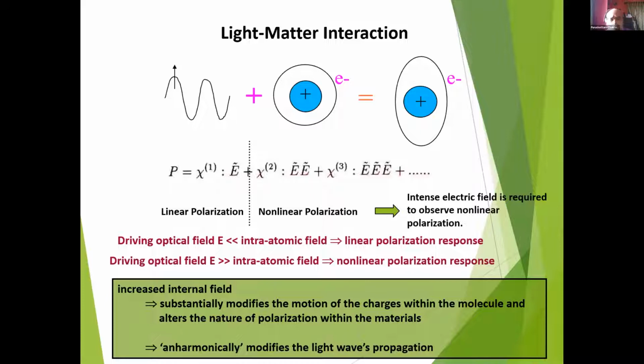Now, polarization is, of course, where the chi2 comes in for the higher optical fields, and chi3 and chi4, chi5, and so on. I will be talking basically about the chi3 part, because I'm talking about photonics, I'm talking about the glasses, I'm talking about the metal quantum dots which are embedded in the glasses. Now, when the driving optical field is much smaller compared to the intraatomic field, you are getting the linear part of polarization. And when the driving optical field is extremely high compared to the intraatomic field, or at least comparable, then you are getting the nonlinear polarization.